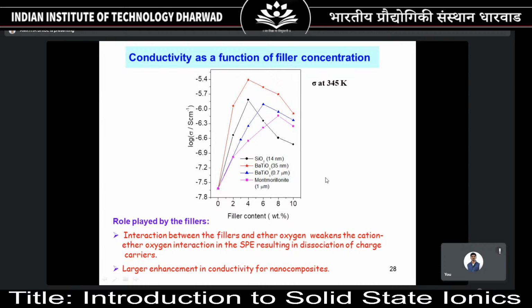Montmorillonite basically is a clay. It contains several kinds of inorganic oxides. So look at this. Out of these, I am very much interested in this barium titanate, which has 2 different particle sizes. The blue color one has particle size of roughly around 0.7 micron, and the red color symbols are the 35 nanometer, which is on top. So by adding about 4-8% of fillers, you could get enhancement in ionic conductivity from -7 to -5. That means you got 2 orders of enhancement in ionic conductivity when you used composites.